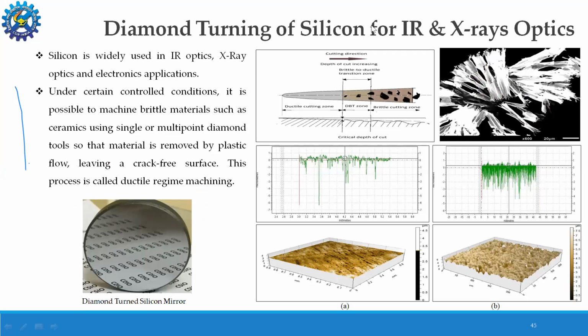Further, we are also associated with the diamond turning of silicon, which is one of the most difficult materials to machine because of its brittleness, for X-rays as well as IR optics, for the focusing of the X-ray beam and guiding the beam to a particular location. So we have optimized the process, and to a very good extent we could achieve a crack-free surface.